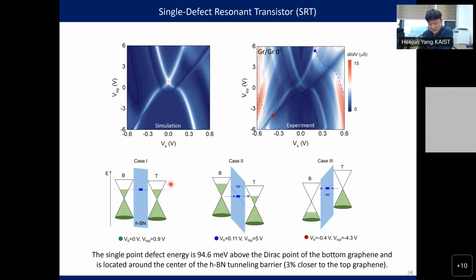And in the paper, I wrote like this about the defect state in the hBN. The single point defect energy is 90 meV above the Dirac point of the bottom graphene. And the single defect state is located around the center of the hBN layer, but 3% closer to the top graphene. They are too detailed, right? So this detailed information, how can you get it? It's from the simulation, of course. So some people are studying defect states in some media, and for 2D materials, this is, as far as I know, the most detailed information about defect state. I'm proud of this finding and simulation.